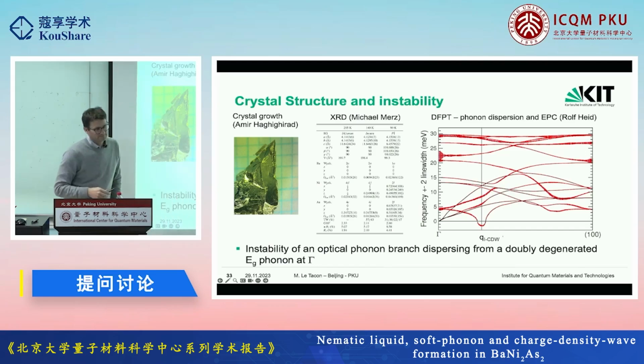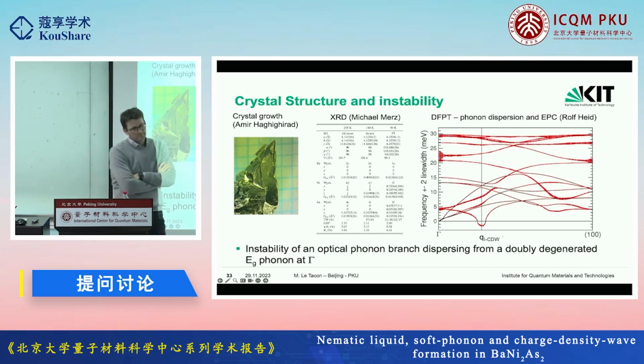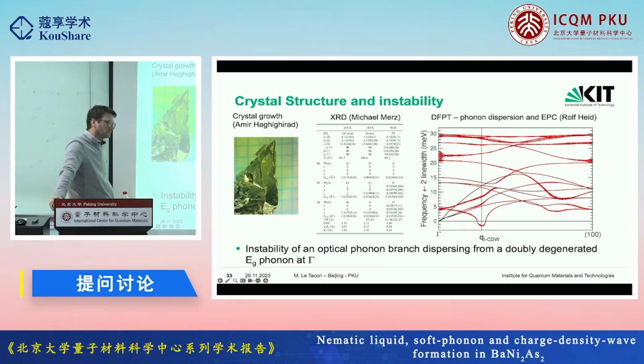But yeah, from the merit of the optical spectroscopy, the material here is absolutely not a standard charge-density wave. Well, but again, you're referring to the 1/3, 0, 1/3 commensurate charge-density wave? Yeah, the charge-density wave basically for these materials, the structure phase transition, you actually see the spectral change over very broad angular scale. If it's a charge-density wave, basically you see a kind of gap opening just below, something like that, low energy physics. But here, we look at this material, it changes over maybe several eV or something. So it's not low energy physics here after the phase transition.